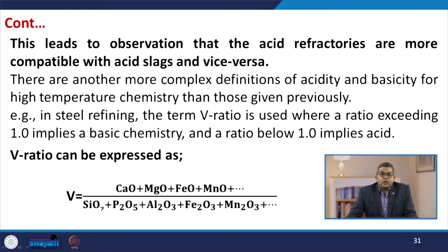Now, this led to an observation that the acid refractories are more compatible with acid slag or vice versa. Now, there is another, more complex definition of acidity and basicity for high temperature chemistry than those given previously. Like in steel refining, the term V ratio is used, where a ratio exceeding 1.0 implies a basic chemistry and a ratio below 1.0 implies acid.